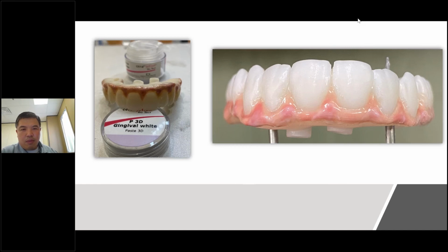So with that said, we gotta make sure that we can control our temperature correctly. Without controlling the temperature, you will have a fracture rate coming out. So what is the difference in controlling the temperature on your oven? We will have to control them on the cooling cycle. The ramping up is not going to be much different than what the company tells you for your pink porcelain or your 3D paste. The difference is that when you're cooling down, we have to cool it down slowly with the oven chamber closed.